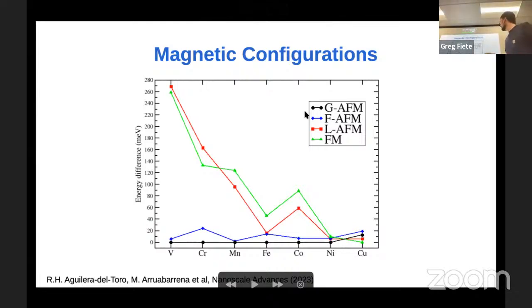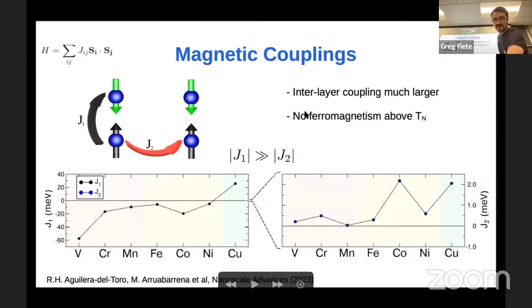So well, here we have another way of showing the same data, where we observe that even though in most of the compounds these two configurations, the GAFM and FAFM, had a similar trend, below half filling the other states were much higher energy. And above half filling, we have some odd-even oscillation of these states going up and down in energy, where we again see some peak in cobalt, indicating that it might be different. So we move to the magnetic properties.